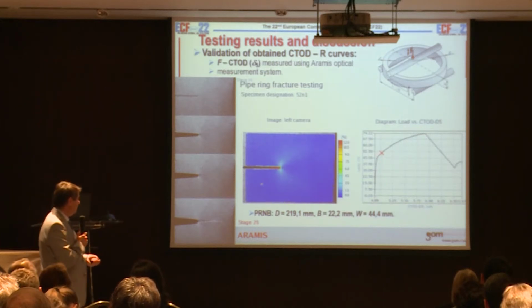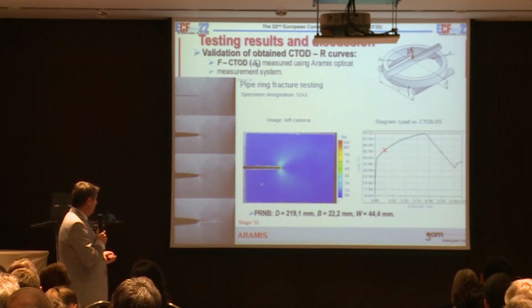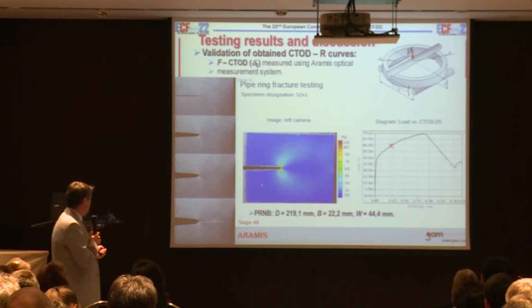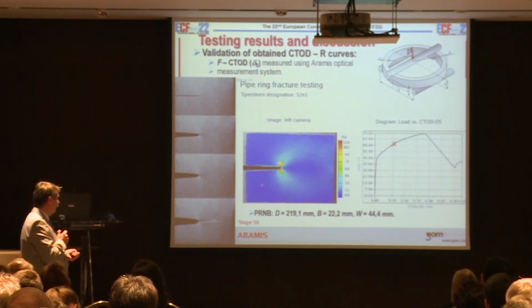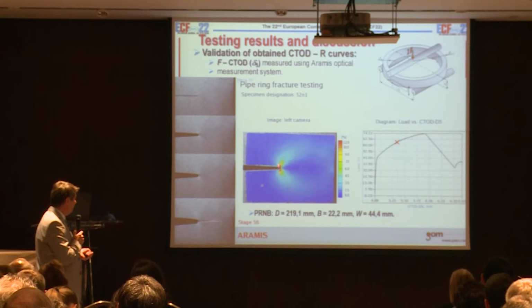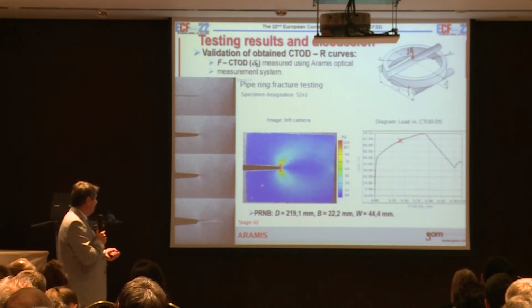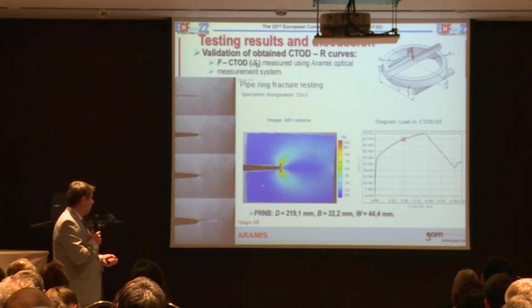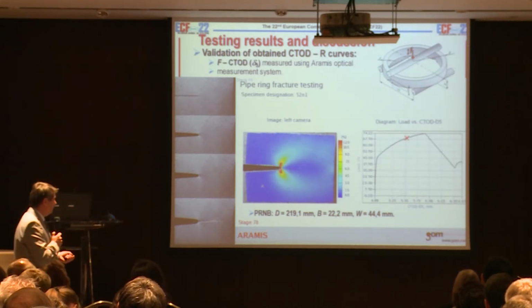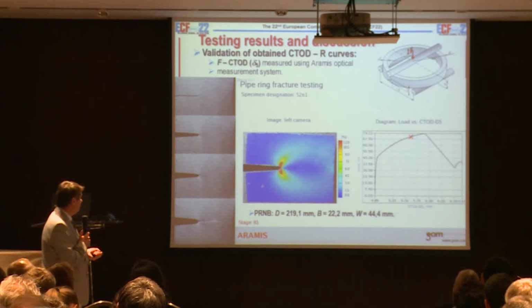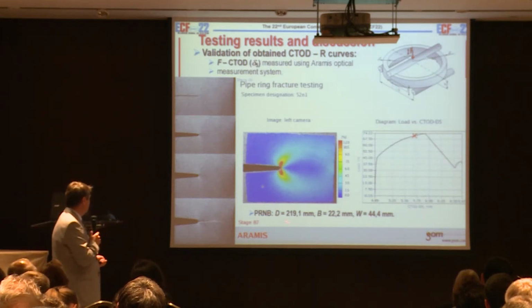In order to have the test running by ARAMIS, you can see here the loading curve. Here are these 2 points at 5 millimeters directly measured, and you can see the crack opening during the test, and then we will have, of course, the drop. So instability of this pipe ring with the fatigue pre-crack.